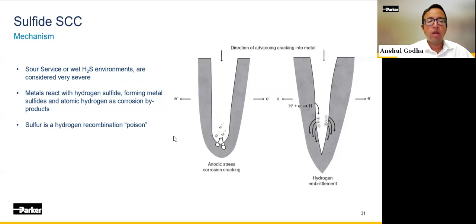This gas is fairly common in offshore applications, especially lately where we are going towards more and more aggressive environments for getting our oil yields. Essentially, the hydrogen sulfide gas acts as something called a hydrogen recombination poison. What that effectively means is that in the presence of hydrogen sulfide gas, the hydrogen atoms tend to diffuse more and more into the metal instead of combining outside the metal and dissipating away. So with increased diffusion, the rate of cracking also increases significantly.